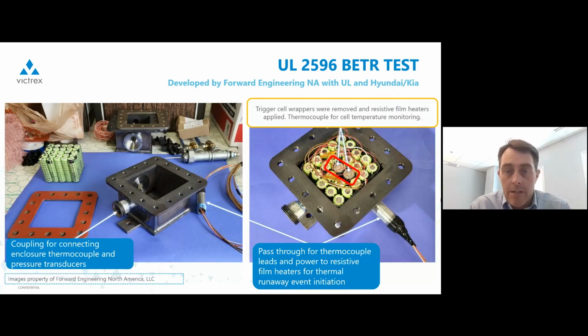So here's a picture of the actual test setup. You can see the steel box and you can see the basket of batteries there. There are some coupling connectors for the thermocouples that are attached to the batteries throughout the inside of the box, as well as the inside of the composite sheet. In the right-hand image, I've circled two cells in the middle. With these, the wrappers were removed from the cell. You can see they all typically have a greenish shell, but those wrappers were removed and a resistive film heater was applied. That resistive film heater builds up heat, it's that heat blanket around the battery, which then triggers the thermal runaway.